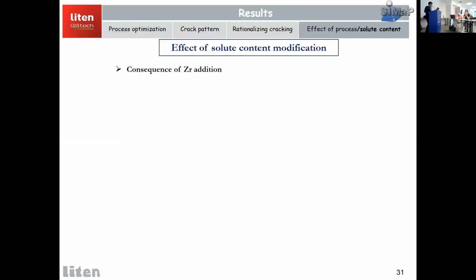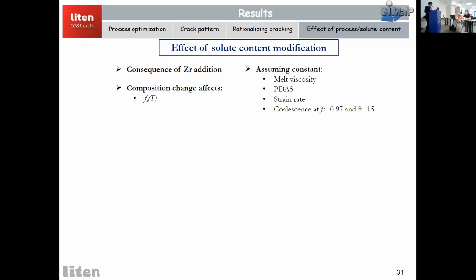So we did several solute content modifications to the standard 6061 aluminum alloy. But here I will be presenting just one particular case, which is the zirconium addition. Zirconium addition is widely reported in the literature to be cracking mitigating. So the idea is whether the mitigation with zirconium can be captured by the RDG model or not. To do that, we just changed the solid fraction, the solidification path of the alloy, assuming the rest of the metallurgical parameters are kept constant.